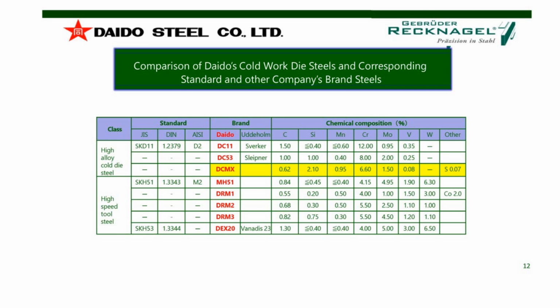6.6%. And very interesting is that DCMX has a content of sulfur, and in this case sulfur is very important to improve the machinability. The sulfur content is very limited, like the salt in a soup, and it has no negative impact, no bad impact on the mechanical properties. That's very important to know. It's just to bring up the machinability. We will see it a little bit later in the slides. So let's go forward.